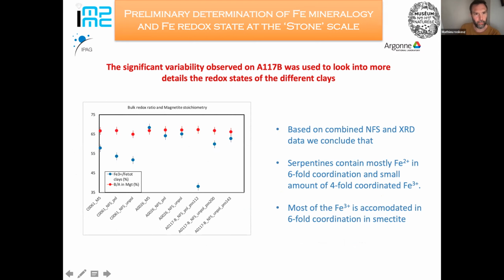If you look at the bulk redox ratio, this is the result we have in blue, and the spectrum that I just introduced, A117B, has a very, very low redox state as compared to the other grains. This is very interesting because this tells you that serpentine is much more reduced than smectite. Most of the iron 3+ that we measured in clay minerals is accommodated in the smectite.